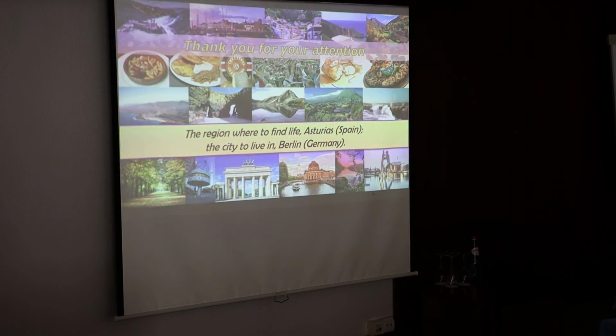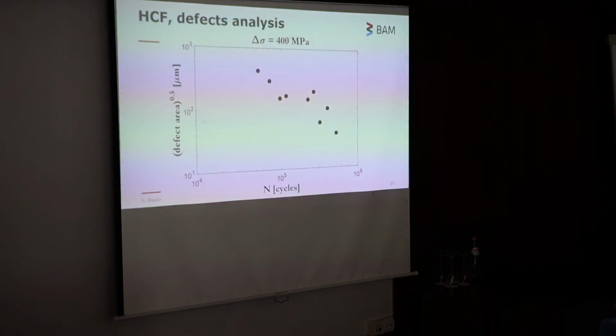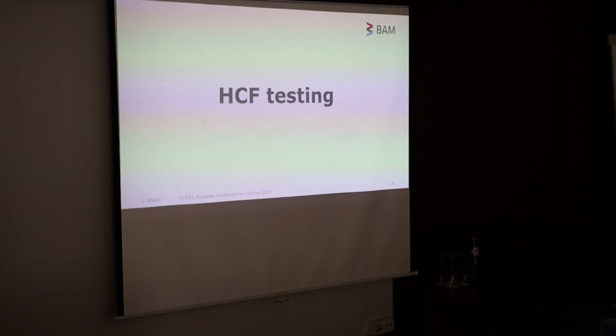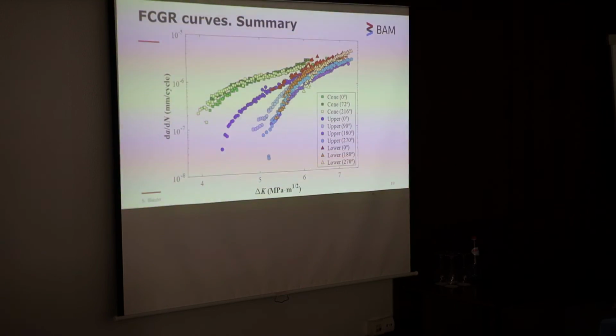Yeah. Are you referring to the fatigue test? Yes. Because in this case, in the high cycle fatigue test, we have information about the residual stress on the surface, and we have removed the surface layers in order to minimize those effects. But it's true that in the case of the fatigue crack growth test, we have no information about the real condition. So, in fact, we think that these results, for the cone part, are probably because the effective load ratio is much higher than the expected one. In principle, we are working at 0.1, but probably in this case there are no closure effects. So we assume that is the reason, but we need to check.